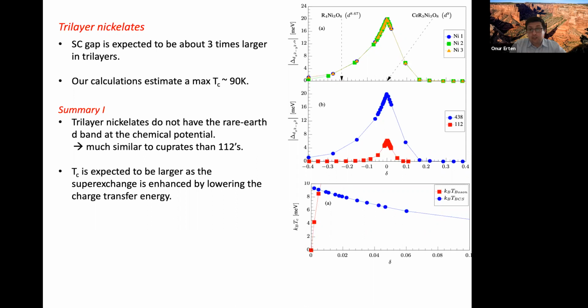All right, so this is the summary of the first part, which tells that if you make tri-layer nickelates, you get rid of the rare earth D band at the chemical potential. And this makes the system much more similar to cuprates than the 112s. And then we expect the TC to be larger, mainly because the super exchange is enhanced due to lowering the charge transfer gap.